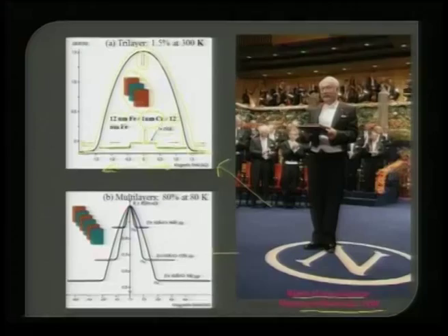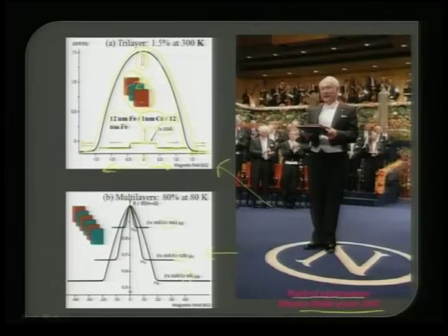So, Albert Fert actually brought out this notion. He said, I can try to make several of these bilayers, instead of just a trilayer, and everywhere I will try to change the spacer layer thickness. So, that is what he did. If you have chromium as 1.8 nanometer or 1.2 nanometer or 0.9 nanometer, as you bring down the spacer layer smaller and smaller, you can see there is a tremendous fall in resistance, and also the field sensitivity is quite bright compared to even this example.